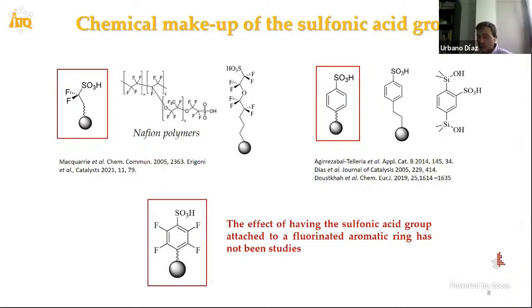It is known that the presence of the effect of fluoride units close to sulfonic groups, as in Nafion polymers, is a good example, and the aromaticity of the groups close to the sulfonic groups is very important to determine the final acidic character of the sulfonic groups. But up to now, the influence of these two factors, the presence of fluorine and the aromatic character of the organic groups close to the sulfonic group, is not very well studied in the literature, this matter being studied in the Multi2ICAT project.